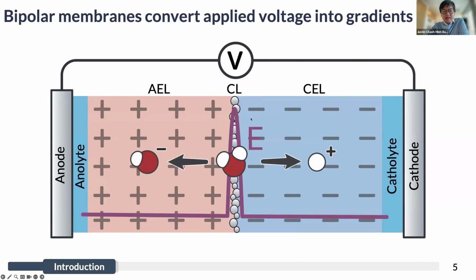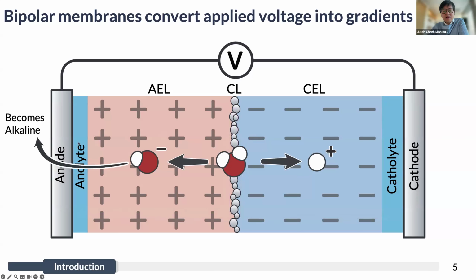So water at this interface under this large electric field will split into protons and hydroxides. The protons will go into the cation exchange layer because of the selectivity of the cation exchange layer for the proton. Hydroxides will go into the anion exchange layer. And this creates an increase in the pH of the anion exchange layer side and a subsequent decrease in pH of the cation exchange layer side.